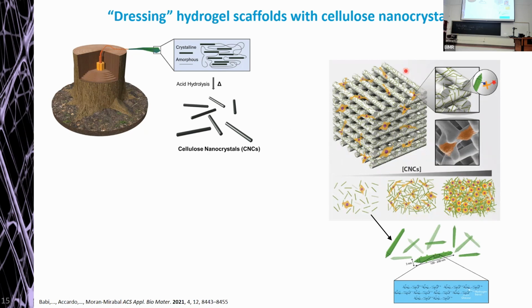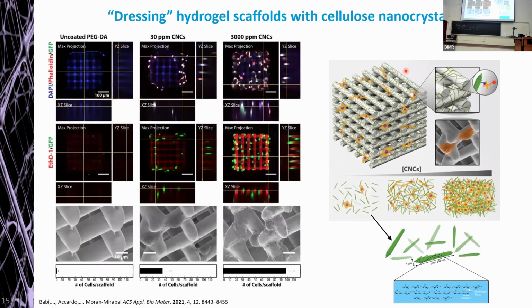And we tested them in the presence of mammalian cells to see, among the other things, if there was a correlation between the concentration of the CNCs and the colonization efficiencies of the cells. And long story short, by performing a multi-technique characterization involving confocal microscopy as well as scanning electron microscopy, we saw a correlation between the percentage of the CNC coating and the ability of the mammalian cells, in this case PC3 cells, to adhere and colonize the scaffold, which makes it very interesting because PEGDA by itself is bioinert. It's biocompatible, but bioinert. So CNCs provide a fully natural biochemical coating for the culture of mammalian cells.